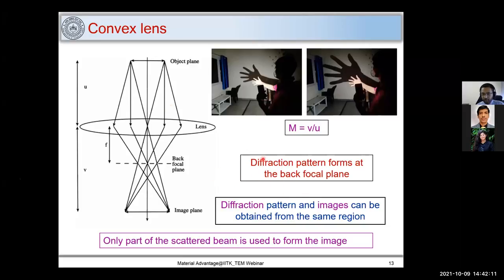And where this diffraction pattern forms, we have seen in an earlier image also, this plane is called the back focal plane, where you can get diffraction information from the sample. And from TEM, we can get both a diffraction pattern as well as an image. However, we can only converge these electron beams. So it is very important to understand that we are not using all the scattered beam. We are just using a part of the scattered beam to form an image. This is an important point, and that is why the apertures in TEM play an important role.